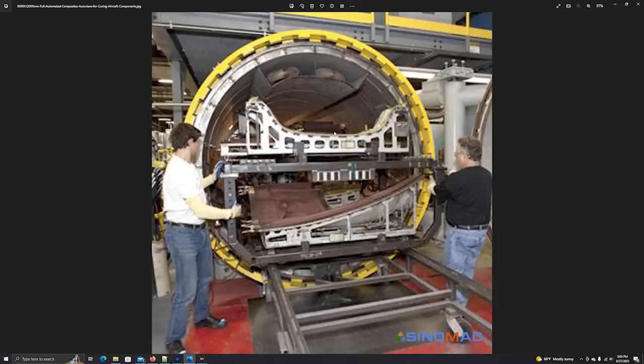Now, the aerospace industry and the racing car or Formula One industry, when they make their chassis, all of the components are put in an autoclave, and the material is heated and pressurized to cure and make sure those plies are compressed together. Now, remember I said when you're vacuum bagging, you only get about 14.7 psi. When you're using an autoclave, you can get anywhere from 40 to 100 psi of pressure. And again, the Formula One industry and the aerospace industry exclusively use autoclaves. Now, after you watch the video of Oceangate filament winding their pressure vessel, they did not use an autoclave.